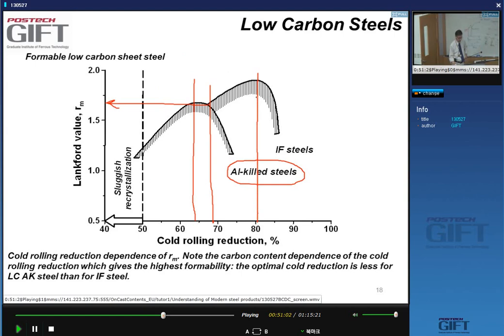In the case of IF steels, the forming properties only become worse with increasing cold rolling deformation beyond 80% of the deformation. So you can give a lot more deformation to your strip, yes? And it also means that it recrystallizes much faster. Yeah? Recrystallization is very fast.